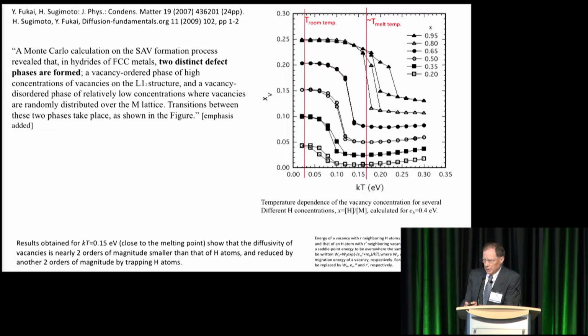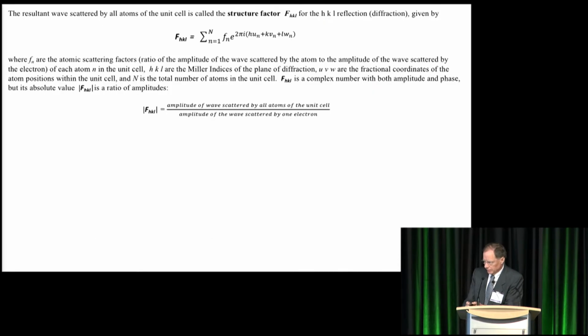This was a calculation done prior to the X-ray diffraction detection. This was in 2007, and a 2017 paper reported the finding that was found in this particular calculation, where there were two forms of the superabundant vacancies, one with a higher concentration of vacancies than the other one.